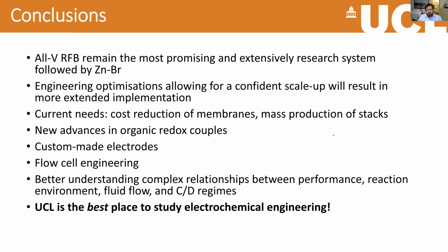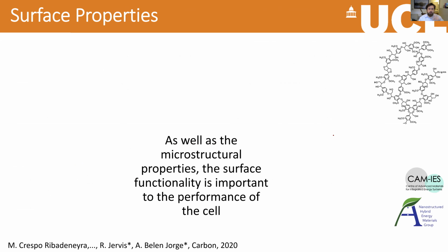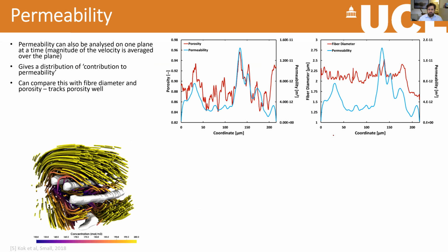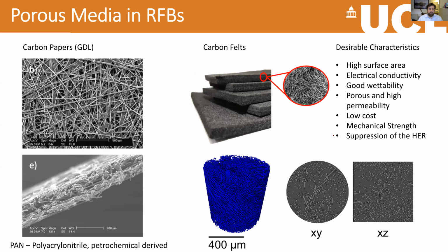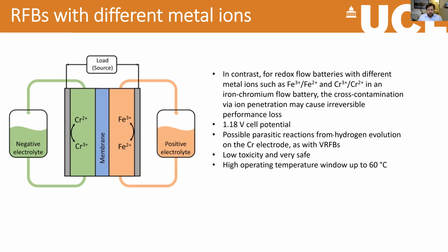However, as I mentioned in a few of the slides, there are things that can cause the depletion of these electrolytes in terms of the capacity that they hold, in terms of the useful charge that we can put into them. One of those is the crossover. So this is the movement of active species through the membrane separator into the wrong compartment. So if we go back to our view of the vanadium flow battery, for example, or let's take the iron chromium one. If we have some species passing over from the chromium side into the iron side, that effectively reduces the amount of chromium that we have in our negative electrolyte. And of course, the amount of reactant is related to the capacity of the battery by Faraday's law. So we immediately then reduce the capacity.